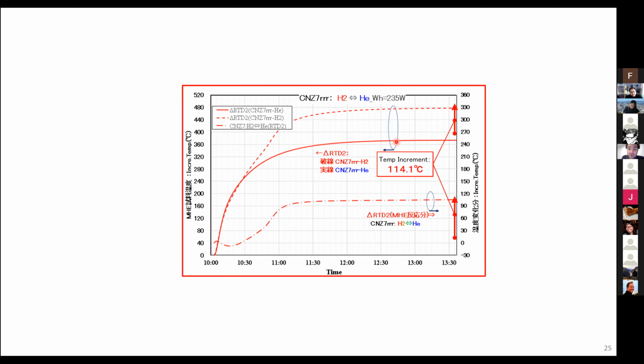In their control runs, they heat the system and they get an equilibrium temperature, which is the temperature that would be expected based on the calibration. But if they have both the palladium nanoparticles in their samples and they use the hydrogen, then they get this big kink here, this bump, and so that difference between the calibration and the active run is the reported excess heat in their results. And so you see it's quite significant. It's over 100 degrees centigrade of difference.